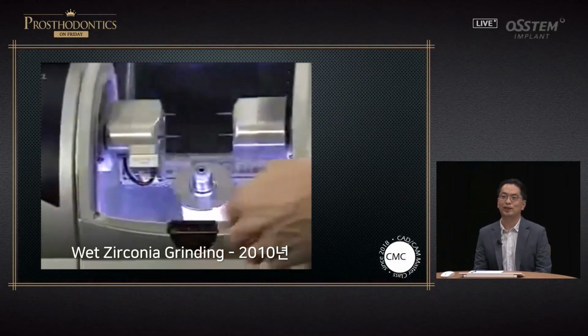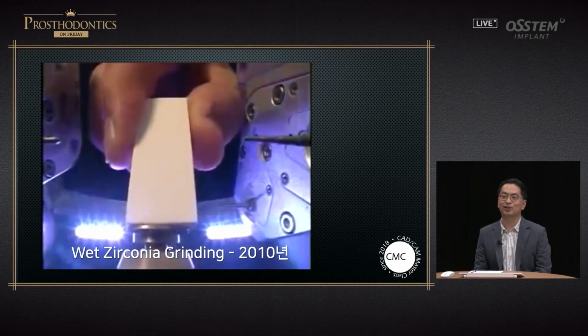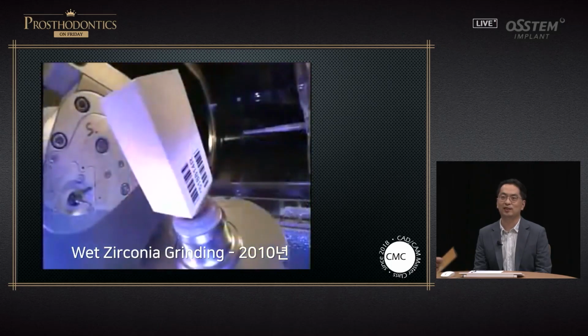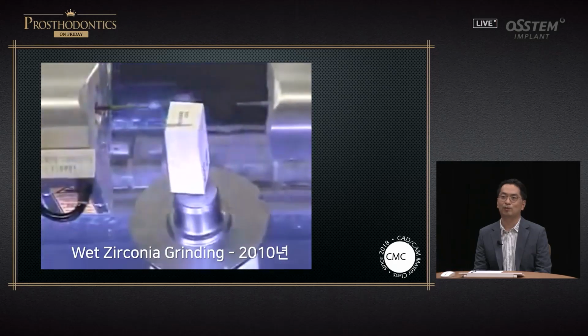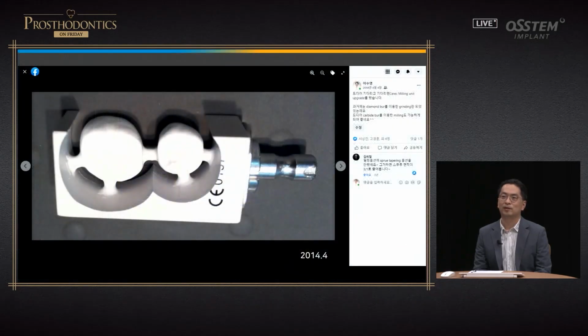first was wet zirconia grinding. A diamond burr was used for fabrication. In 2014, carbide burr milling was introduced. About 10 years ago, I used a CEREC OmniCam, and a CEREC MCS milling machine was used to provide prostheses. Carbide milling was introduced in 2014. At the time, I thought this was awesome, but looking back, it has a lot of room for improvement.